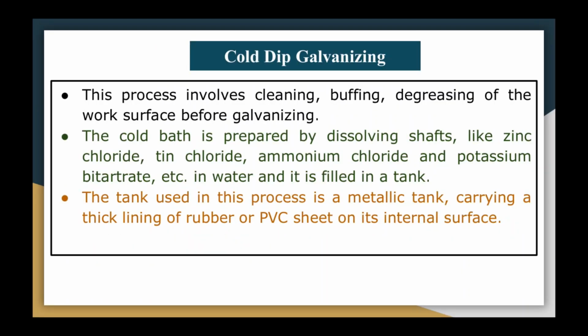Let us discuss the last galvanizing method, that is cold dip. This process involves cleaning, buffing, and degreasing of the work surface before galvanizing. A cold bath is used in this process. No heating or flow of current through the electrolyte solution is required. The cold bath is prepared by dissolving salts like zinc chloride, tin chloride, ammonium chloride, and potassium bitartrate, etc. in water, and it is filled in a tank.